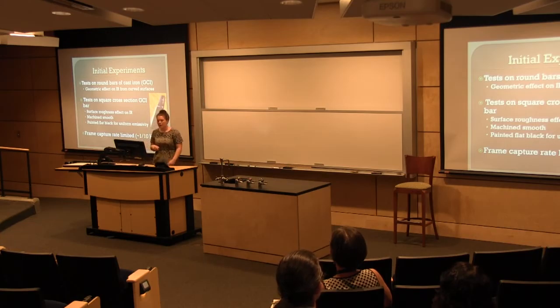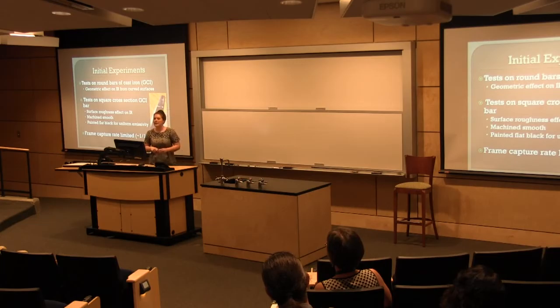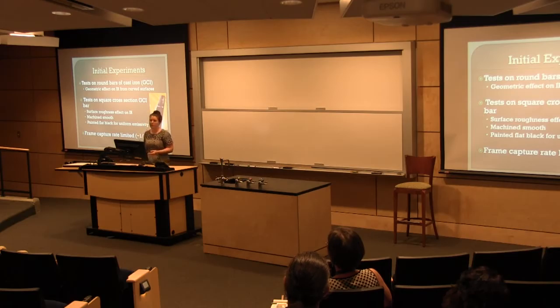And then the last issue we had here was the frame capture rate of the camera is about 6 to 7 seconds for one image for the camera I showed you before, and we're experiencing this in about 1 to 3 seconds. So that was a huge problem for us. So we really had to try to work through that and see where we could go, find another camera.